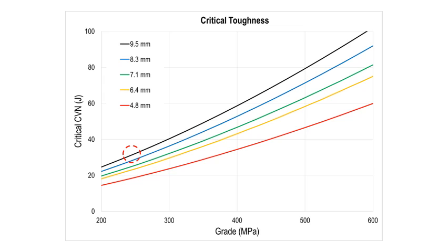Meaning, if you know that you have more than 30 joules of toughness in the pipe, then essentially the fracture term in the equation is going to disappear and you are okay to do a calculation without specifying exactly what the toughness is because that whole term is going to disappear. Now, this is not to say that you're necessarily going to treat the flaw as a metal loss flaw, but you are going to take into account that that fracture term has disappeared.